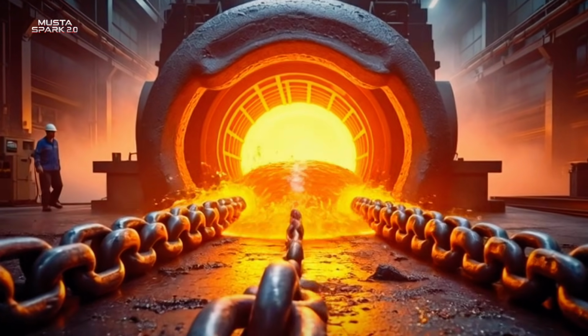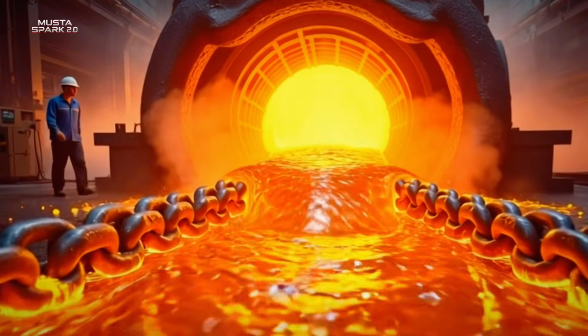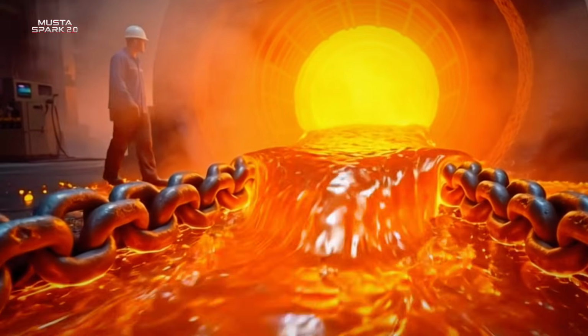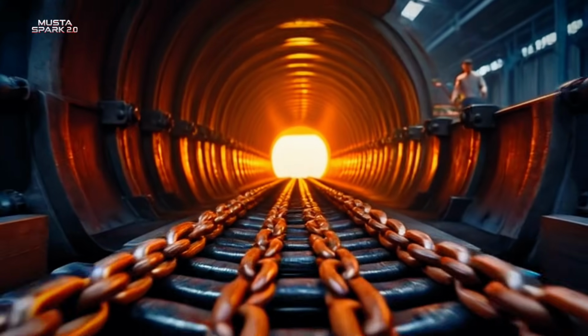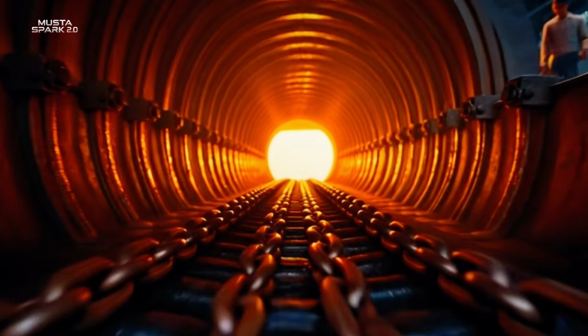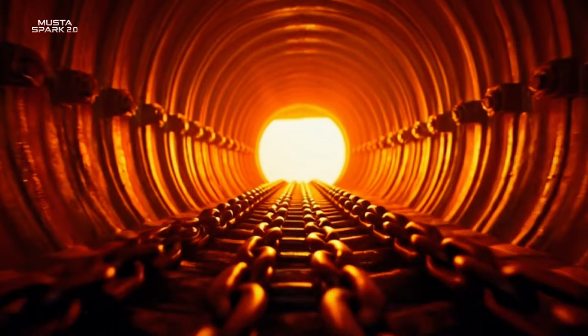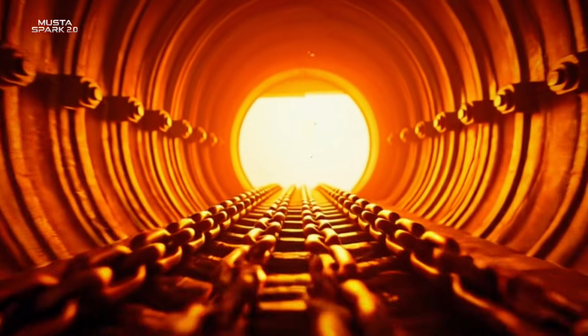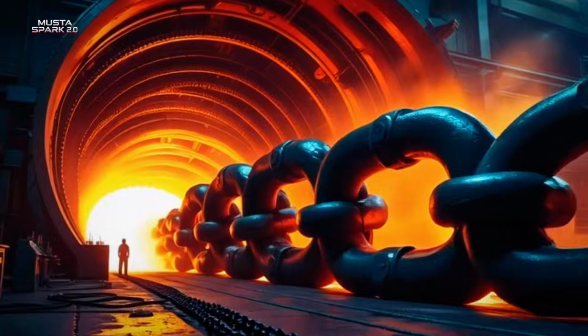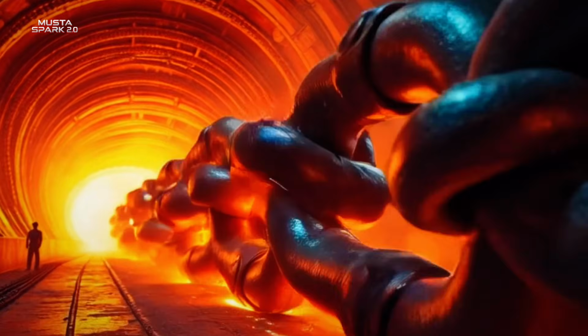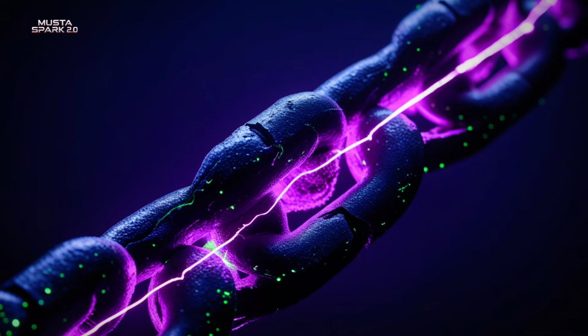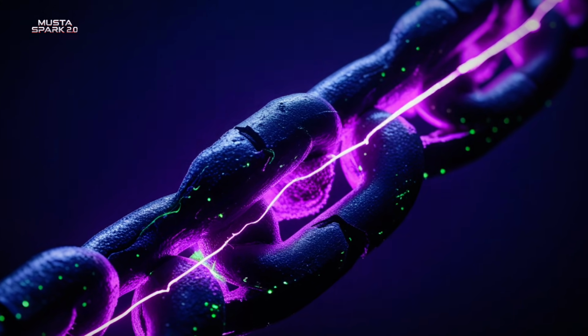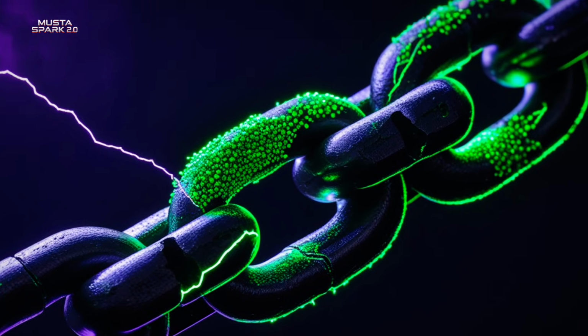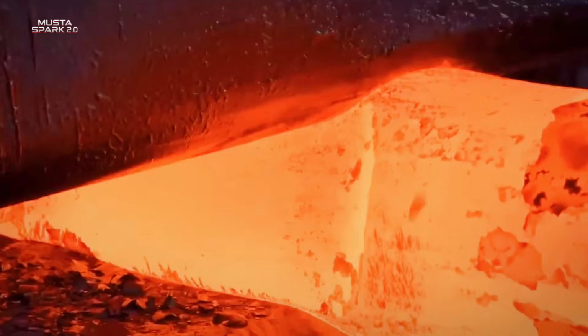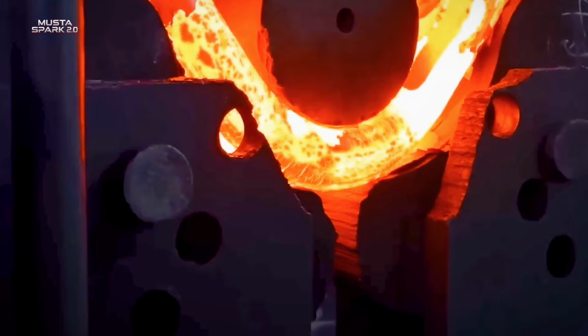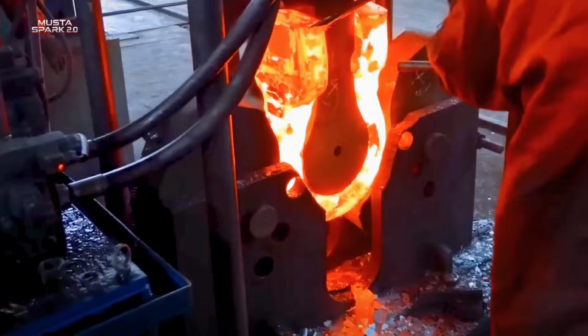The specific temperatures, the duration of each heat treatment stage, and the cooling rates are all precisely calibrated for each grade of chain, each diameter of link, and each specification requirement. This isn't guesswork. This is decades of metallurgical science and real-world testing compressed into a recipe that must be followed exactly every single time. After heat treatment, the chain is visually different. The surface may have a different color, but the real changes are invisible, locked inside the steel, in the arrangement of atoms you can only see under a microscope. Changes that mean the difference between a chain that holds and a chain that doesn't. And in the world of anchor chain, that difference is everything.